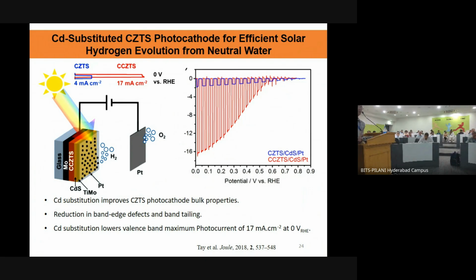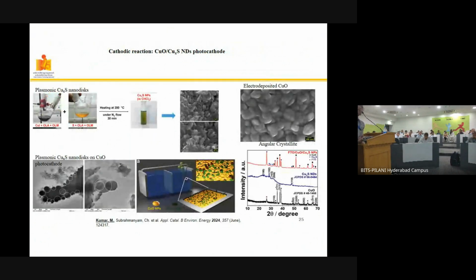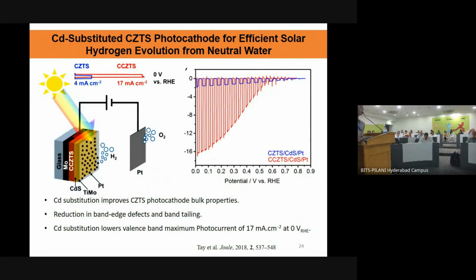This is mainly because the band edges are being tailored, and cadmium substitution lowers the valence band maximum. You look at that at neutral conditions, for example at 0 volt, which is the theoretical potential for hydrogen evolution, you practically see huge currents reported under these conditions. Taking a clue from this, we realized that, having copper, we all know that the reduction potential of copper is only 0.34. It's much easier to oxidize copper.